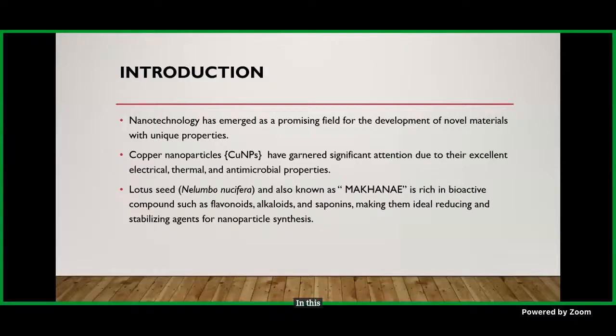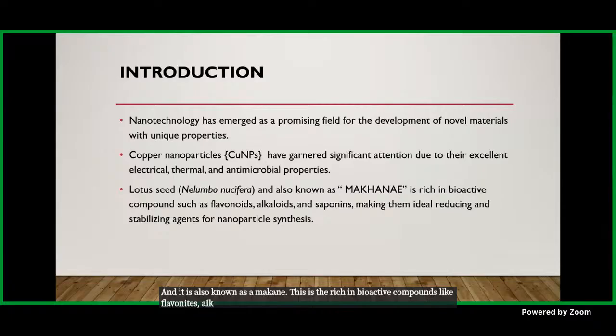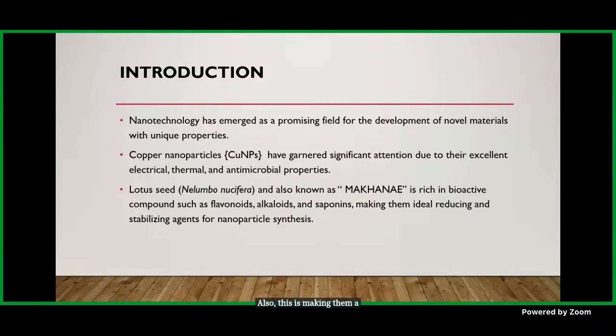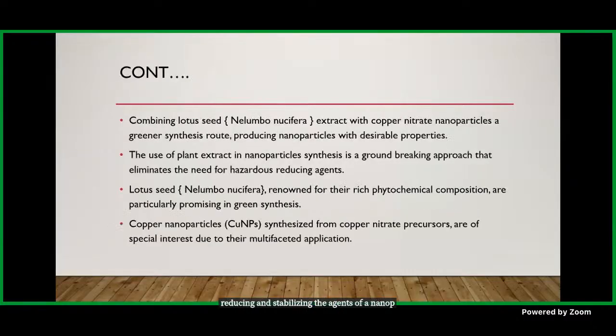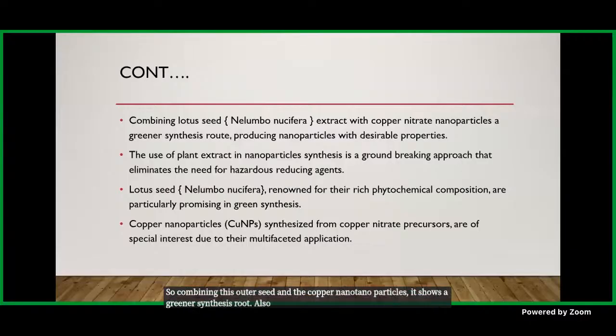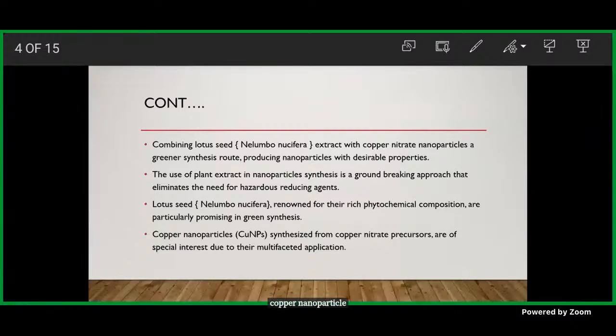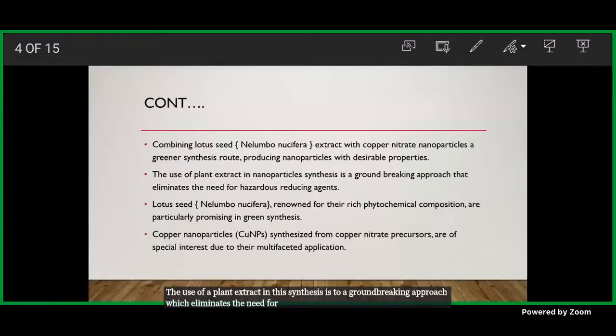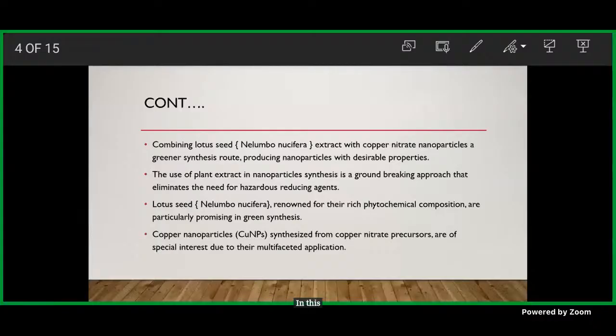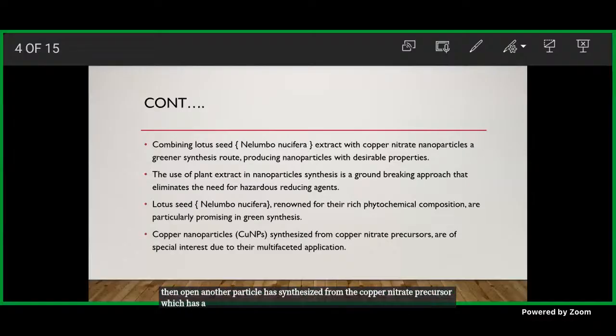In this copper nanoparticle synthesis, I used lotus seed, whose scientific name is Nelumbo nucifera, also known as makhana. It is rich in bioactive compounds like flavonoids, alkaloids, and saponins, making it ideal as a reducing and stabilizing agent for nanoparticle synthesis. Combining lotus seed and copper nitrate shows a greener synthesis route and produces copper nanoparticles with desirable properties. The use of plant extract is a groundbreaking approach which eliminates the need for hazardous reducing agents. Lotus seed has a rich phytochemical composition, which is shown in the green synthesis. Copper nanoparticles synthesized from the copper nitrate precursor are of special interest with multifaceted applications.